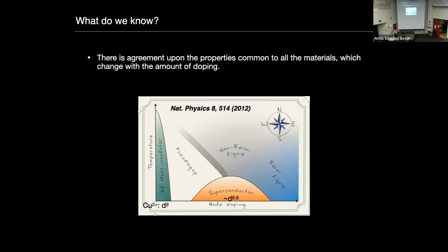In cuprates, there is also good agreement in terms of certain properties that are common to all the materials and that change with the amount of doping. And those are reflected in a prototypical cuprate phase diagram, which is what you see down here, where on the y-axis we have temperature, on the x-axis we have hole doping, or a change in the chemical makeup of the material. A very similar phase diagram, by the way, can be obtained for electron doping, but the one that we can map to the nickelates is this one. That's why I'm going to focus on that today.